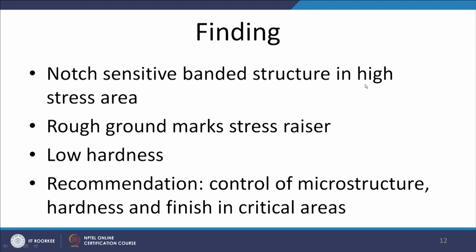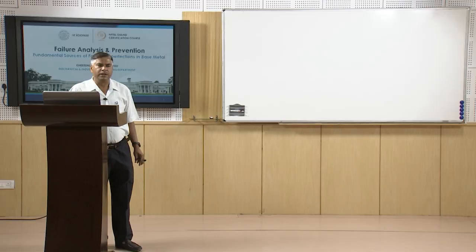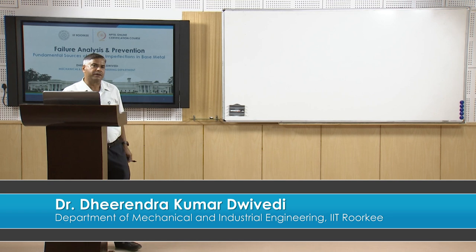The presence of rough ground feed marks, the banded structure, and somewhat lower hardness in high stress areas led to nucleation and growth of the crack, which subsequently led to fracture by fatigue. Notch sensitivity due to the banded structure in high stress areas combined with rough ground marks acting as stress raisers and low hardness resulted in the fatigue fracture of the connecting rod. The recommendation was to control the microstructure properly to avoid banded structures, maintain hardness within 160 to 205 BHN, and maintain proper surface finish in high stress areas.